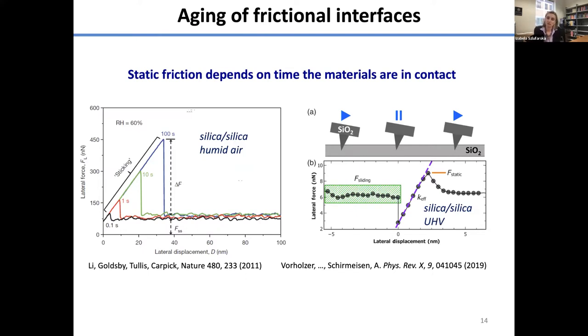Okay, so that's one aspect of that, sort of trying to get to the physics or chemistry of the mechanochemical coupling. I wanted to show you another, what I think is a cool example of mechanochemical phenomenon that has been shown also on the example of silicon. And this is related to contact aging. So it turns out that static friction is not truly static and that it depends on the age of contact. So it depends how long the contact was held in place prior to sliding. So the longer we hold it in place, the larger the static friction.